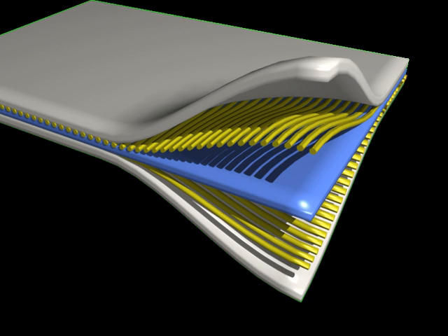Intermediate angles of misorientation theta lead to matrix shear failure. Again, the cross-sectional area is modified, but since shear stress is now the driving force for failure, the area of the matrix parallel to the fibers is of interest, increasing by a factor of 1/sin theta. Similarly, the force parallel to this area again decreases by F cos theta, leading to a total tensile strength of tau_m / (sin theta cos theta), where tau_m is the matrix shear strength.